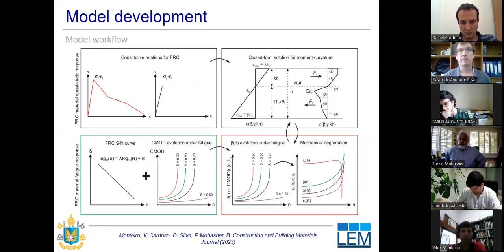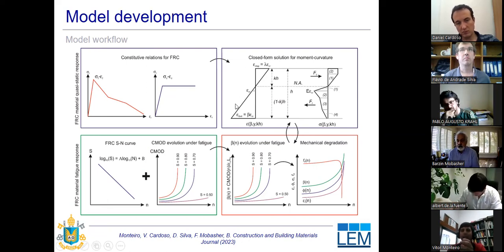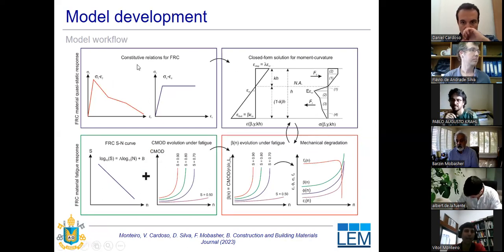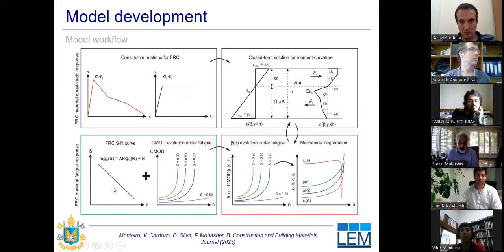So here is the model workflow. The first steps we have already analyzed and discussed. We have the constitutive relations for FRC. Then we apply the closed form solutions to analyze the quasi-static behavior of the material in terms of the stress strain and the applied constitutive relations. Then for fatigue, to analyze the fatigue degradation, we need first as input an S-N curve, which will bring us a number of cycles before failure. So the S-N curve can bring a mean number of cycles before failure to analyze the fatigue degradation.